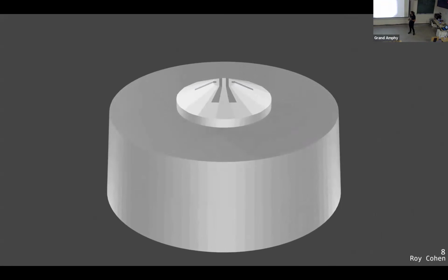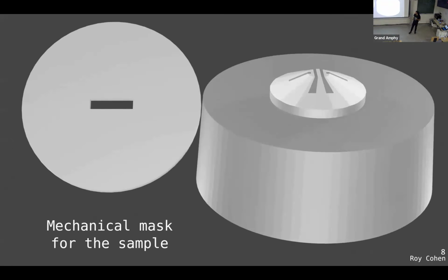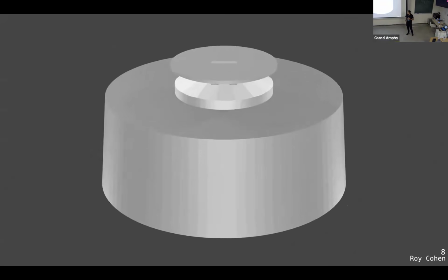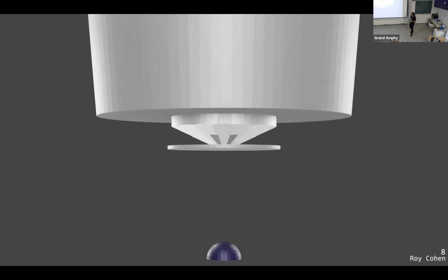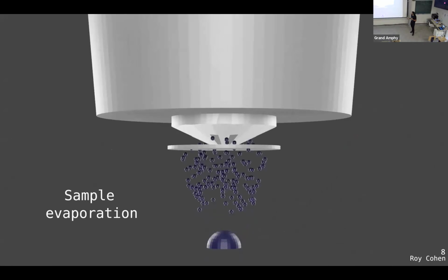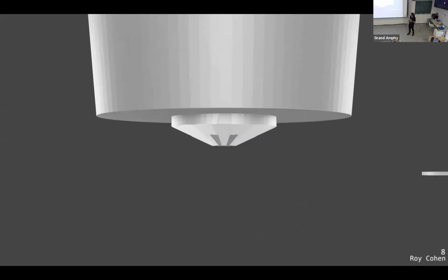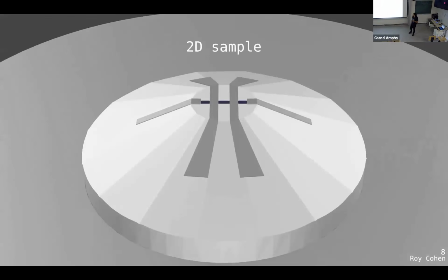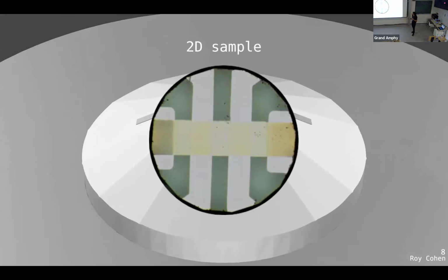Afterwards, we evaporate our thin films, mainly indium oxide, again through a mechanical mask. Nowadays, we have developed new methods with photolithography. So we evaporate our indium oxide in between the contacts on our diamond. Here we can see our 2D thin films on top of the diamond between our contacts.